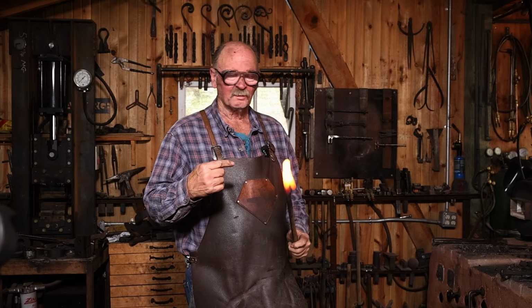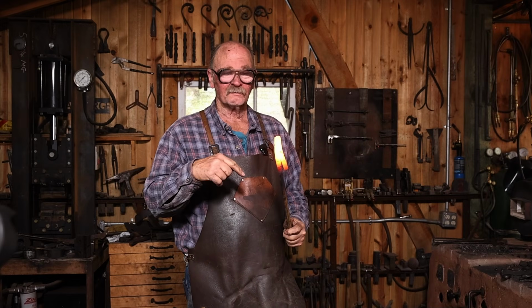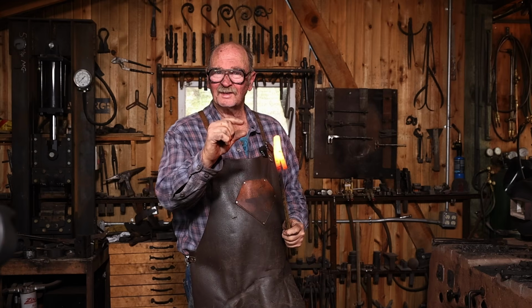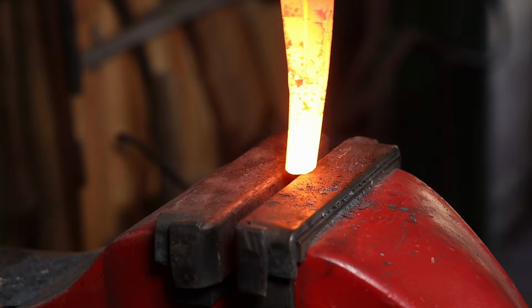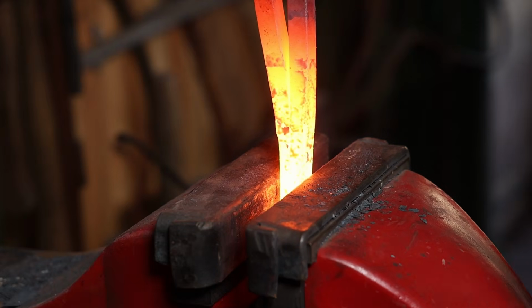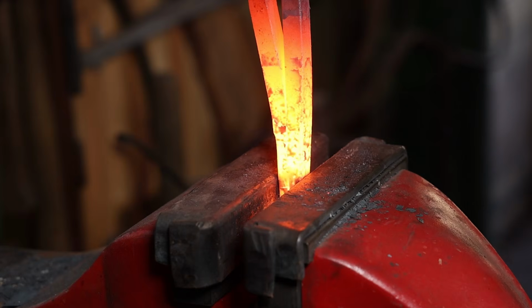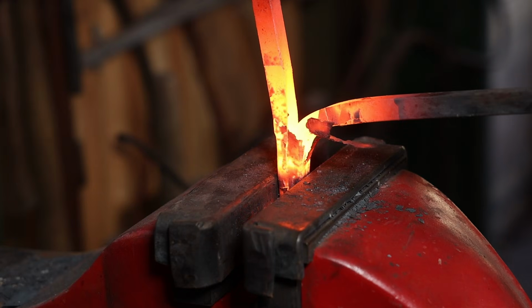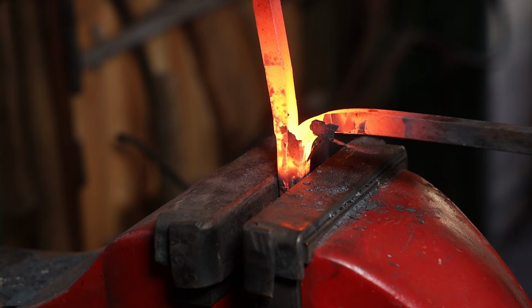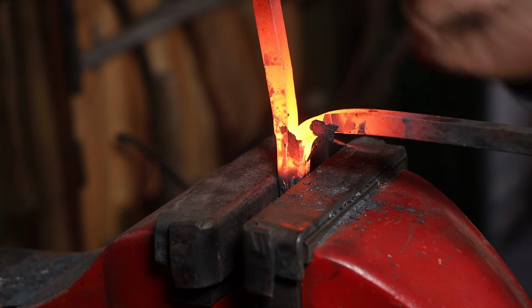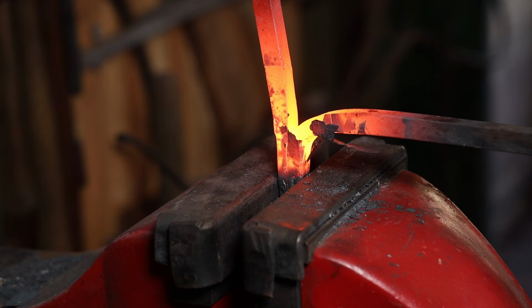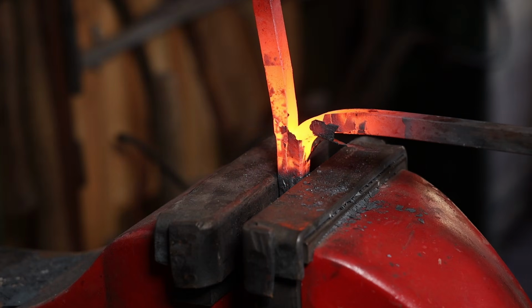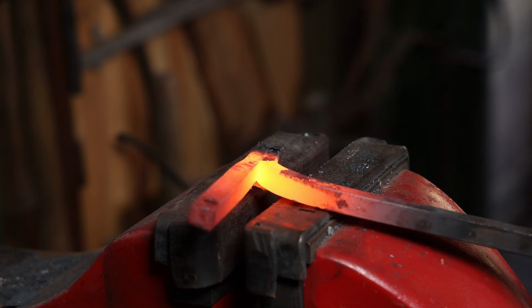Now, I'm pretty comfortable that I've got a good weld. Let's go to the vise, put just the last half inch of that in, bend it over, and see if it opens up. If I've got a good weld, this should not open all the way up. And it bends up here and does not go down into where the weld is, even though that's a thinner area and would want to bend easier. So that's a good weld.